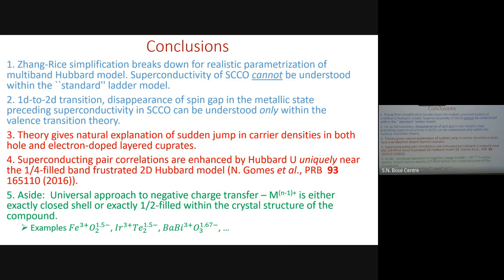But if that is the case, will it be a triplet superconductor? No. It will be triplet only if it goes to iron. But if irons are going to be ferromagnetic, will it not break the singlet pairs? It depends on which Hund's coupling dominates. I don't understand it fully. This is a conjecture. This is 30 years of putting together 4 different fields. But I'm saying people are focused on the cations only. Maybe magnetism is due to cations, the superconductivity and conductivity is due to the anions.